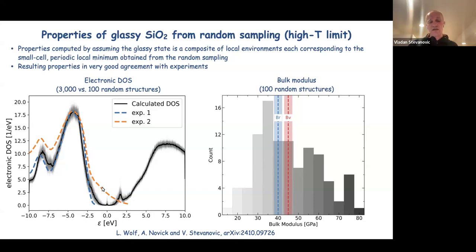And they don't get access to conduction bands. In our case, we do still have underestimation of the band gap. So I assume that this conduction band feature is pushed in reality to somewhere here. Our band gap, if you measure it from our curve, is on the order of 4 volts, whereas in experiment it is about 9. So the underestimation of the band gap by DFT in our result is pretty severe. So I think for the orange curve, probably the gap is not closed. Does that answer? Yeah, okay. Thank you.